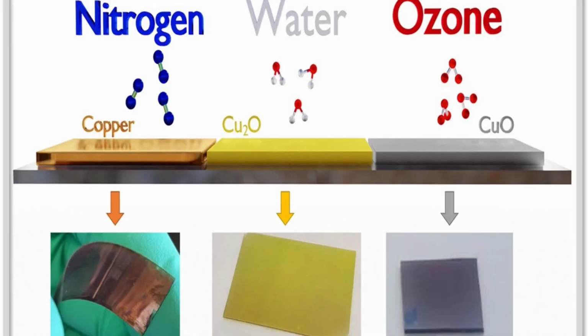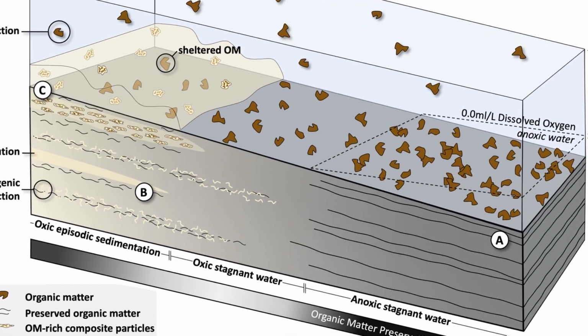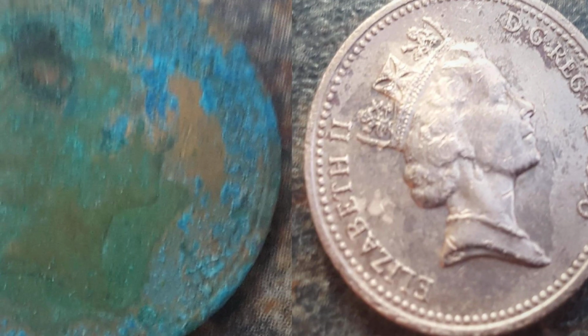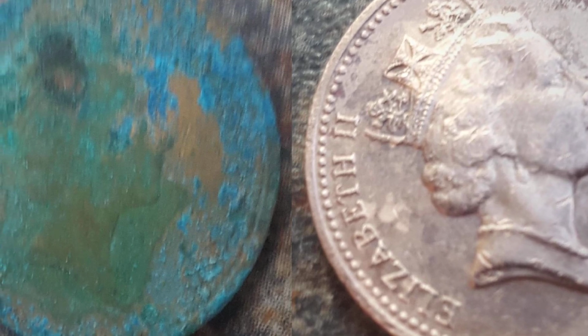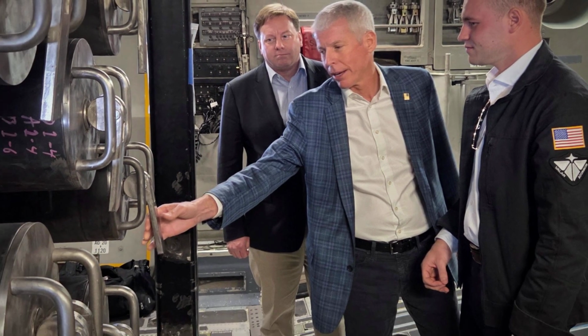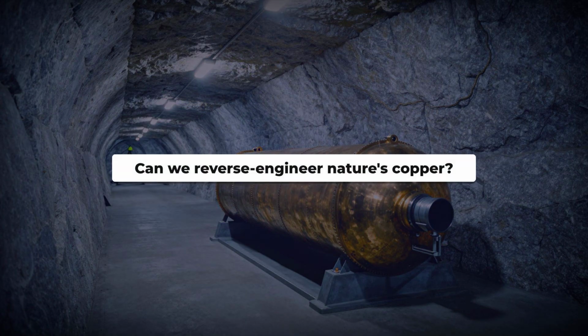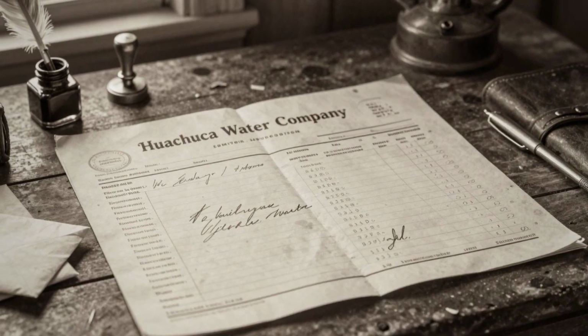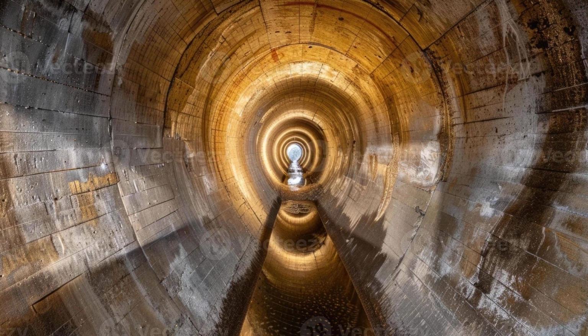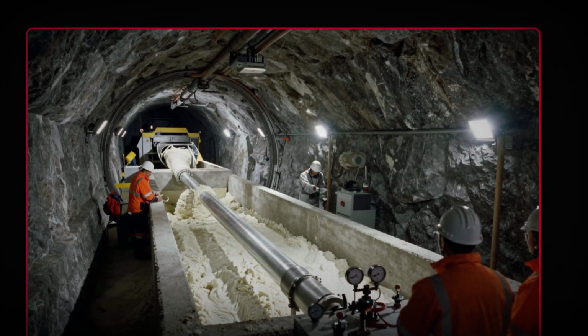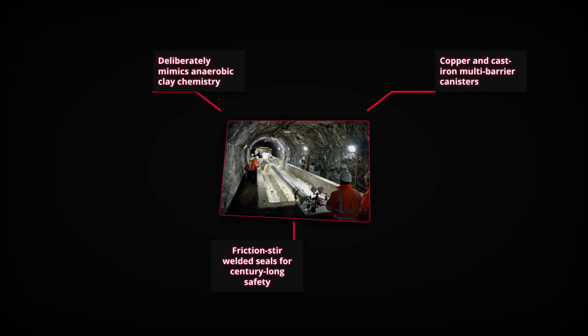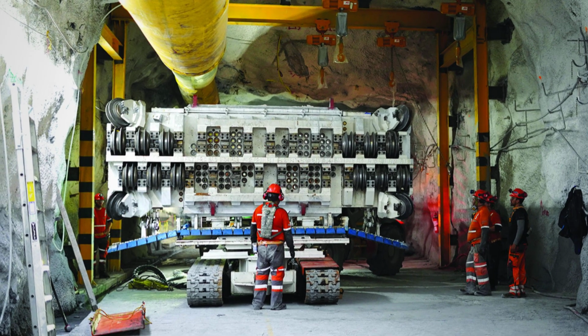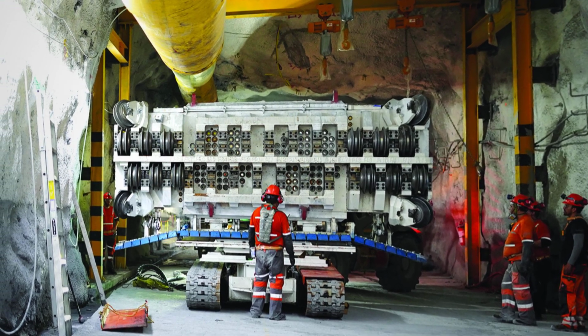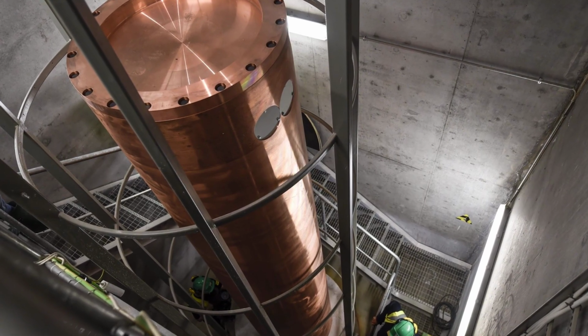The reason is that copper corrosion requires oxygen. In an environment where there is no dissolved oxygen in the surrounding water, the chemical reactions that normally degrade copper have no fuel to run on. They stop. So the engineers asked themselves a simple question: what if we don't try to invent a new material, and instead reverse engineer the conditions that nature has already proven can preserve copper for thousands of years? This is what Onkalo actually is, not a vault, not a tomb in the cinematic sense. It's an environment, deliberately constructed, designed to mimic the chemistry of an anaerobic clay deposit, scaled up to industrial size 400 meters underground.